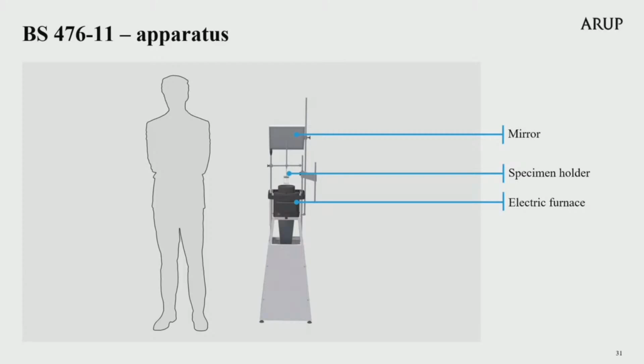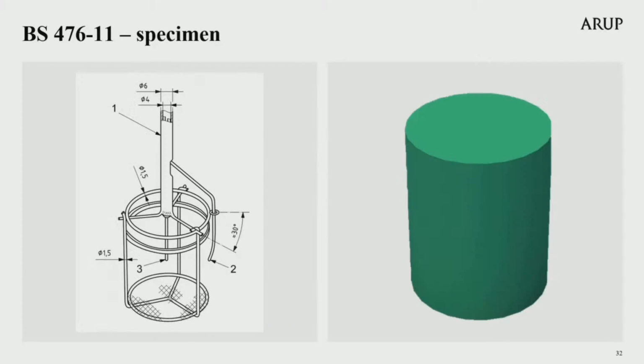Part 11 also consists of an electric furnace with the power input to the furnace such that the temperature measured by the furnace thermocouple is stabilised at 750 degrees Celsius. This specimen holder has a circular base to accommodate cylindrical test specimens. The furnace thermocouple is to be located 10 millimetres from the furnace tube wall and at a height corresponding to the midpoint of the furnace tube. The specimen thermocouple is positioned at the geometric centre of the specimen. A third thermocouple is also added to allow a horizontal contact with the interior of the furnace wall.